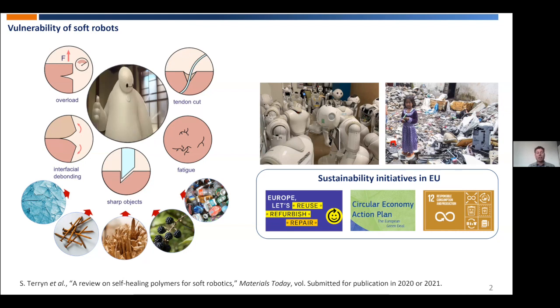And if you have actually multiple materials inside of a soft robot, then delamination occurs also. So it's the interfacial debonding of multi-material interfaces. And all these damages, they actually lead to these robotic systems which have a limited lifetime. And this, of course, leads to non-economic solutions. And therefore, actually, in a lot of applications, this limited lifetime is preventing the large adoption of these soft robotic systems in industrial and in commercial applications.